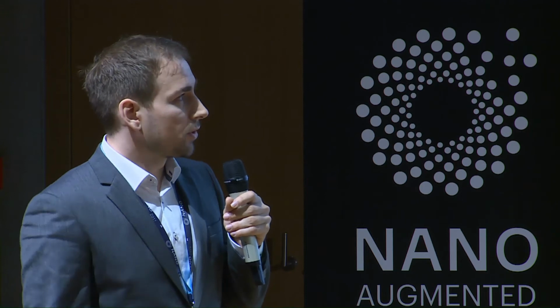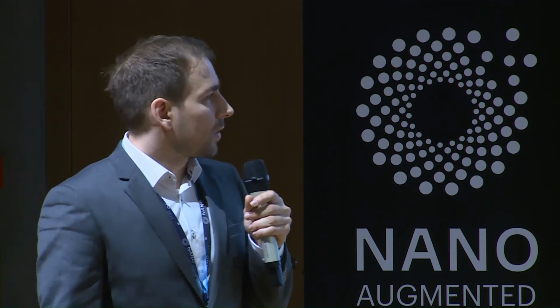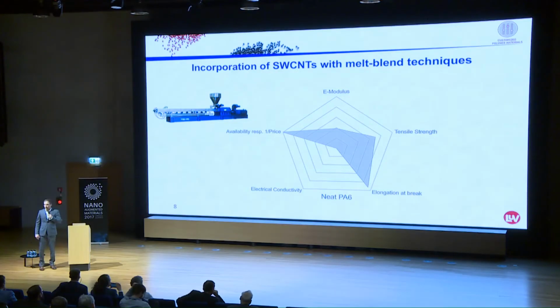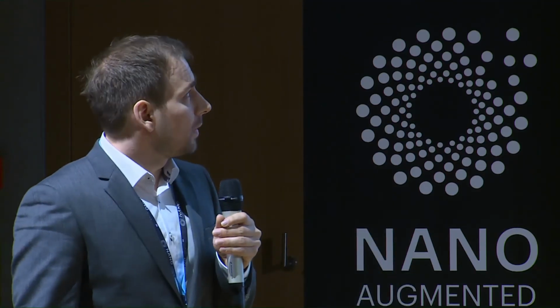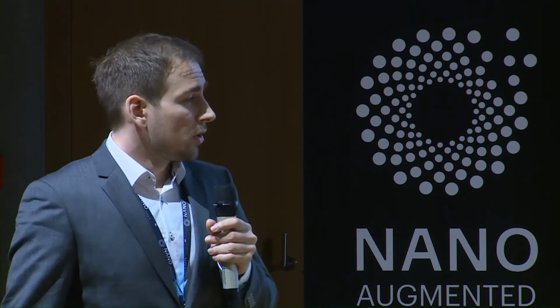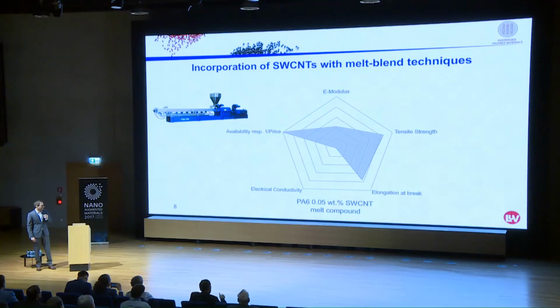We can see here the profile: the mechanical properties with E modulus, tensile strength, elongation at break, but also the electrical conductivity and the availability as an inverted price. And we see PA6, it's quite cheap, it's quite ductile, so we can make fibers out of it, but it's also an isolator. And now let's see what's happening when we use an extruder to incorporate TUBALLs here. With 0.05 weight% of TUBALLs, we directly get an effect on the polymer material.